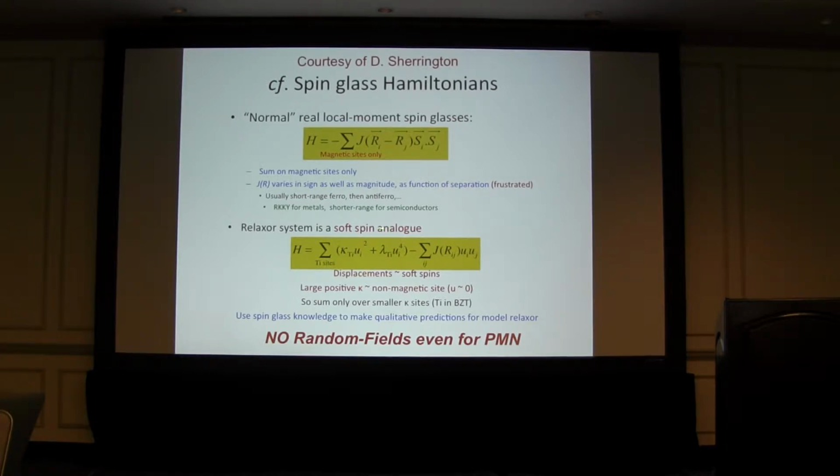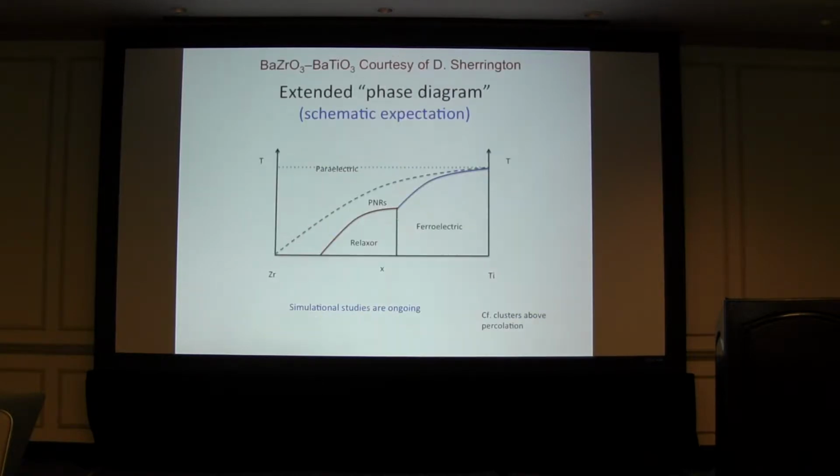And then he had a local displacement term that might be big for some atoms and small for some others, as in barium titanate zirconate, so titanium would be allowed to flop around a fair bit and zirconium would not. And then random bonds of unspecified length or range that provide frustrated interactions, but no random fields, and not even for his adaptation to PMN.